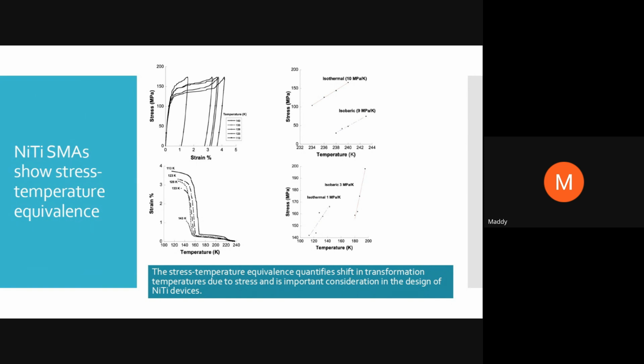And so in real-life applications, where you are subjected to harsh conditions, right? Temperature changes, the stress may change as time evolves for that particular application. So this particular correlation is extremely important for the designer to understand when designing the product, right? What you see here on the left is the stress-strain response at different temperatures, and you can see that there is a shift in the onset stress, and then upon cooling, you can see that the temperature at which these are recovered also changes.